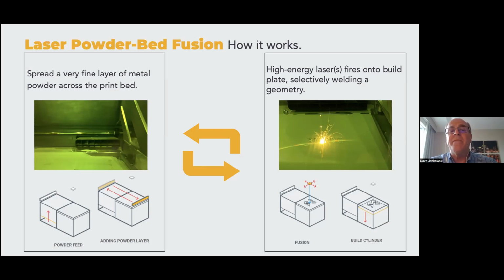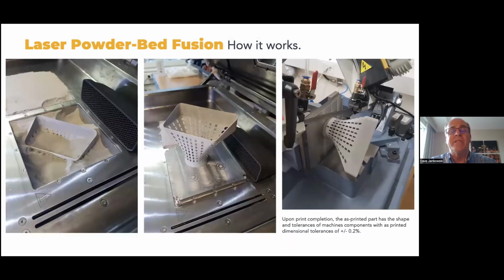In addition, the as-printed dimensional tolerance is plus or minus 0.2%. So that kind of equates to better than rough machine, but not quite as good as finished machine. And as you can see here, some components can be used directly off the printer. This is a great example here of these three photographs.